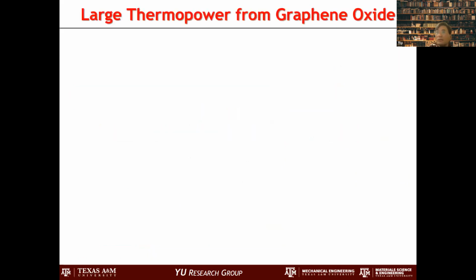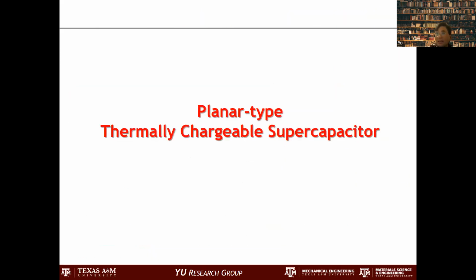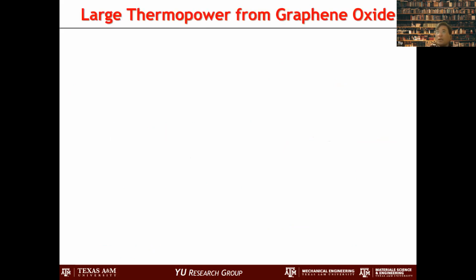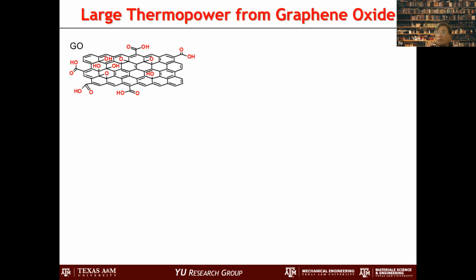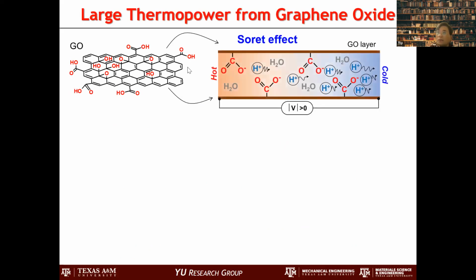I need 2 volt so that I can operate a device. So that's why we developed the planar type thermally chargeable supercapacitor, because we can make a larger temperature difference. In this case, what we use is graphene oxide. And graphene oxide has protons because of the hydroxyl group and carboxyl group. We have a proton that is migrating between the layers of graphene oxide. But this number of protons is not good enough.